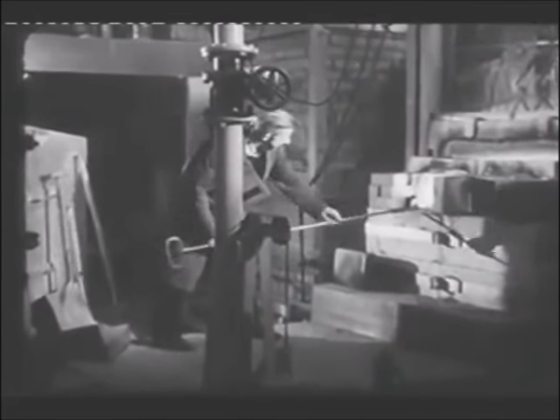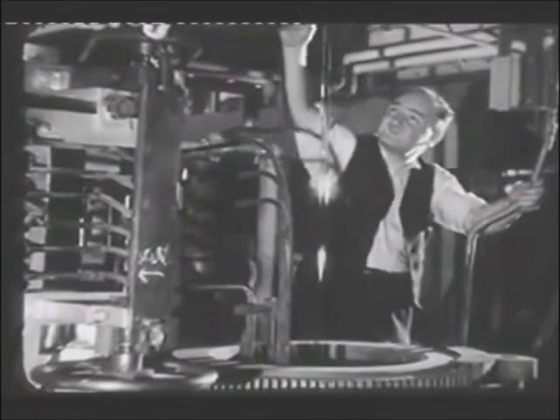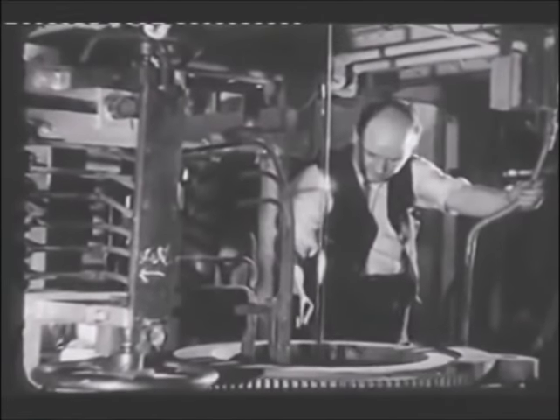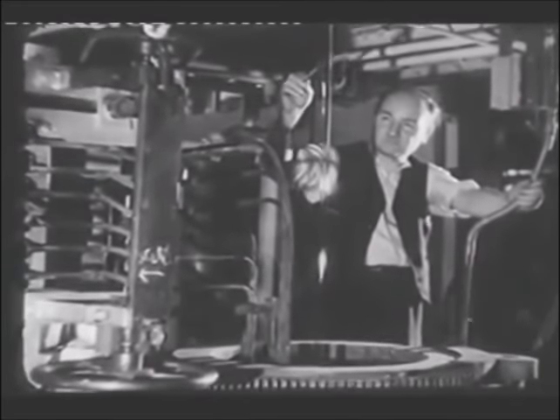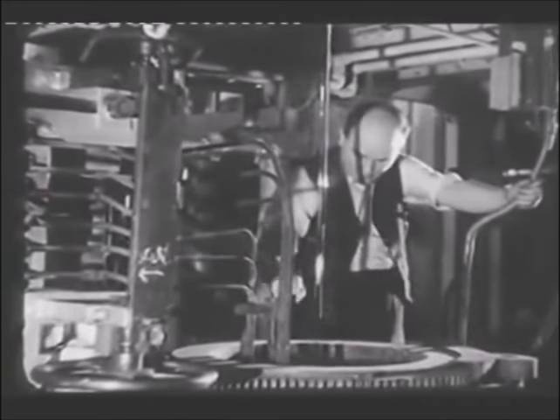Many of the glass parts used in valve manufacture are made from glass tubing. From the tube-making machine, a column of molten glass is drawn upwards, an internal blast of air keeping the glass in tubular form and controlling its diameter. As it ascends, external air streams cool it and control the thickness of the wall.